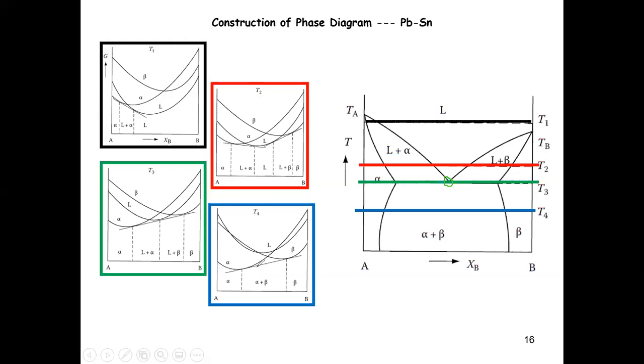Because at very low temperature, the free energy curve is going to be very high, and only the alpha and beta phases play a role here. Now you're going back to the 2-phase region, worrying about 2 free energy curves. So you're going to have a single alpha phase region, a single beta phase region, and an alpha plus beta coexistence region, right? And then you have 2 types of solidus